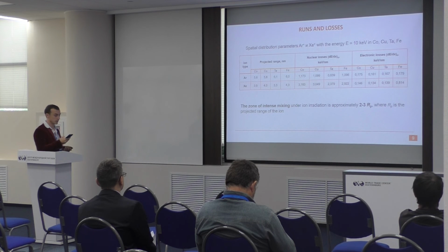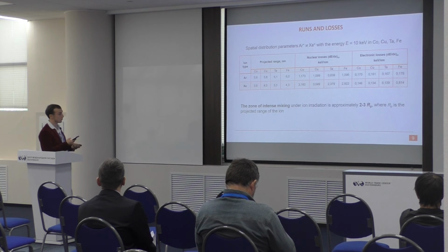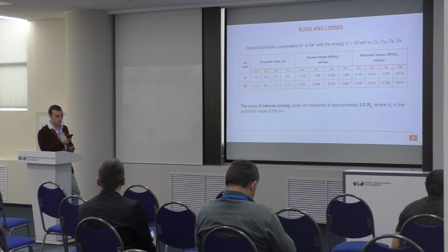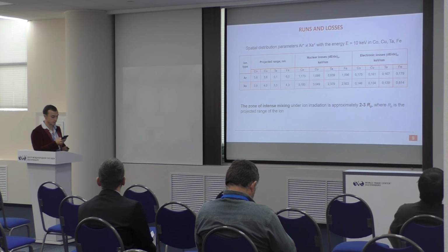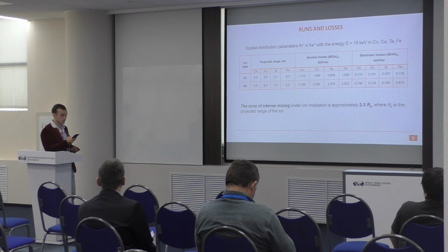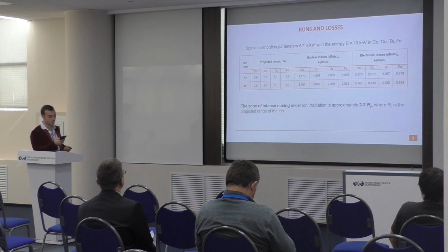The slide shows the theoretical values of ranges and losses obtained by Monte Carlo methods. It is important to note that the zone of intense mixing under ion radiation is approximately from 2 to 3 Rp, as shown on the slide, where Rp is the projected range of ions. The values of the average projected range of argon and xenon ions with energy of 10 keV are shown on the screen.